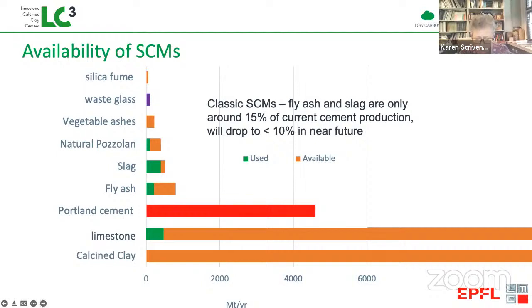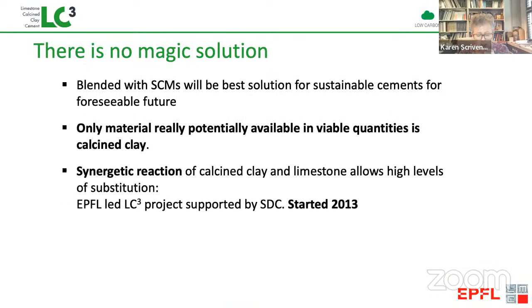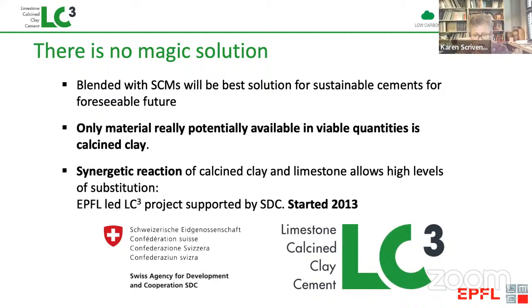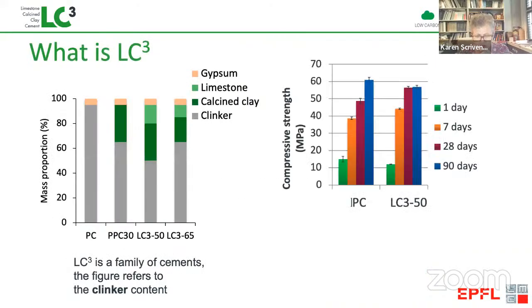So the materials we have that can take this technology of substitution further are really limestone. Limestone is abundant, but the problem is when we go to additions more than about 10%, it just becomes a diluent. And what is really the thing that can change everything is clays, which can be calcined, which become very reactive material. So this was the idea behind the LC3 technology, and particularly the discovery that when we put calcined clay and limestone together, we can get very high levels of substitution.